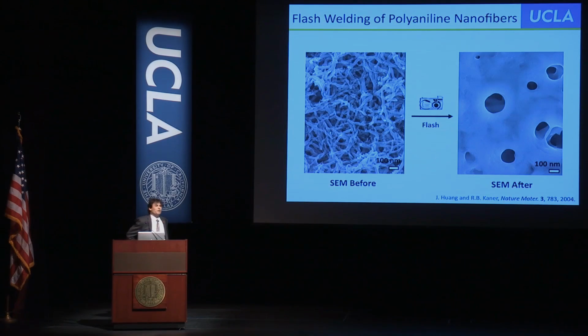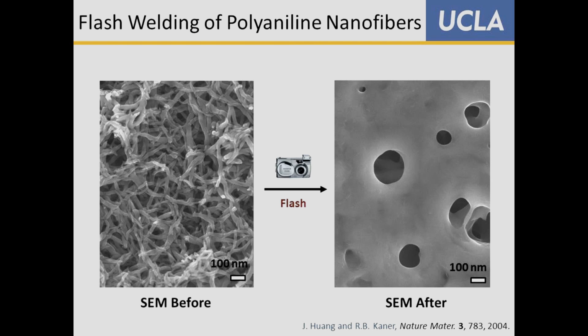Now, I promised that we could actually melt this polymer. And here's how we do it. We took the polymer and we exposed it to a camera flash at close range, and it melts.